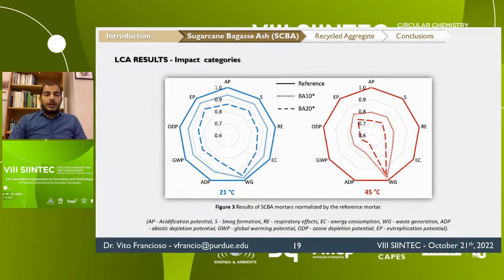As shown before, the life cycle assessment considered 9 different environmental impact categories, which are displayed here in the graphs. For all of them, the substitution of cement with sugarcane bagasse ash reduces the impact. Furthermore, as can be observed here in the graph on the right, the higher curing temperature significantly reduces the environmental impact. Among these, waste generation was the only one that was not affected by the curing temperature.